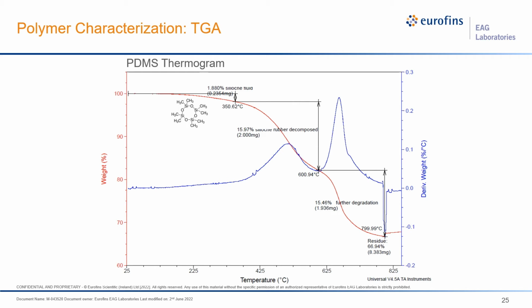Looking at this sample, what we see is it contains about 2% of volatile to semi-volatile materials up until about 350 degrees. This could include small cyclic siloxanes like the D4 that's shown in the spectrum. Next, we see two larger thermal decomposition events of about 15% each. This is actually the PDMS backbone breaking down into smaller fragments and volatilizing and leaving the sample pan. The most important piece of information that we'll take away from this is that after heating the sample to 800 degrees C, 67% of the initial sample mass still remains on the balance.